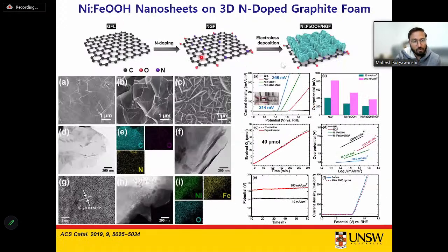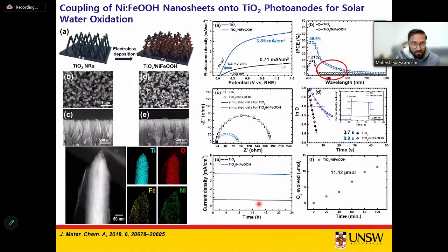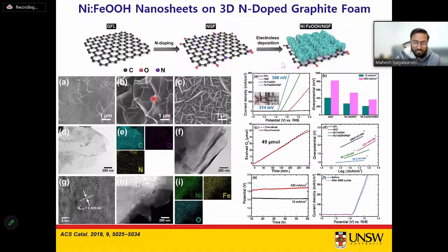Also, again, what we have done, we have used a different catalyst, which is a nickel iron based catalyst, and then we have put it on the TiO2 nanorod arrays. And we have seen that this catalyst is much more stable than the previous one, with the stability over 24 hours without any noticeable degradation, and the improvement in the current density from about 0.71 milliampere to 3.85 milliampere per centimeter square, which is a very, very good result. And this paper has already been published in the JMCA, this one in the ACS Catalysis, and it has been highly cited because of its simple demonstration of this electroless deposition approach to grow this catalyst.